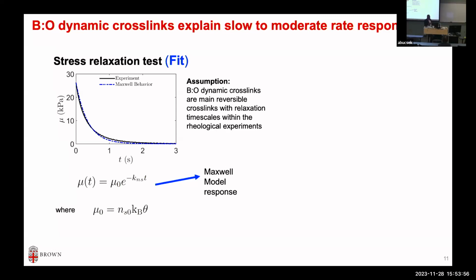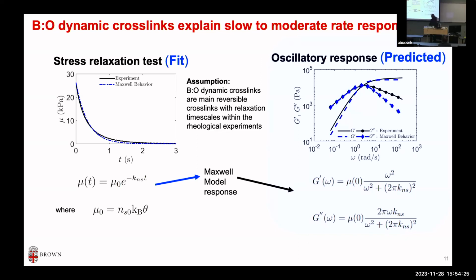But interestingly, that simple assumption of first order kinetics basically gives a behavior similar to a linear elastic Maxwell-like model with one spring and dashpot. And for that model, we can write the quantitative equations for the oscillatory rheology, where you are subjecting the viscoelastic material to different strain rates. You get basically the G prime, G double prime, storage modulus, loss modulus functions. We can have expressions for those based on that assumption. Now, from that one fit, we can predict. We found this very interesting. We're able to predict the G prime and G double prime quite well with that assumption.